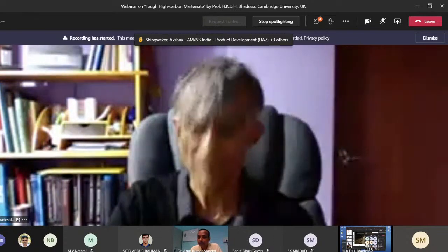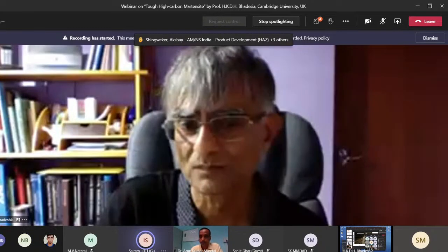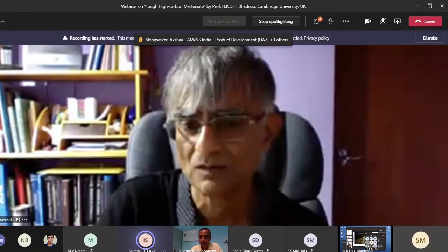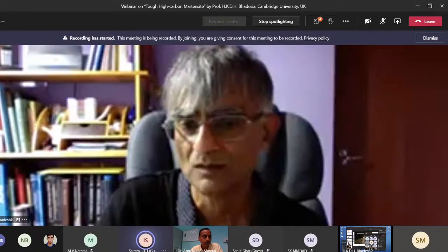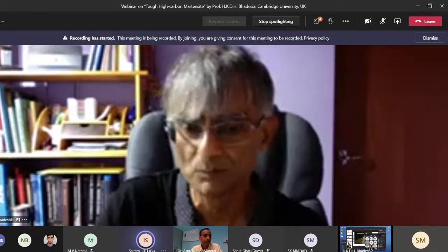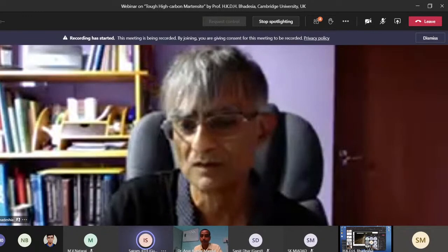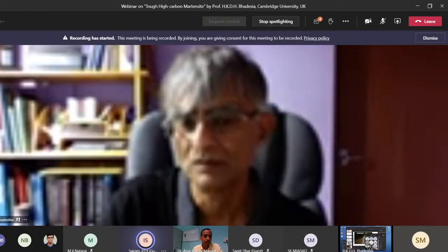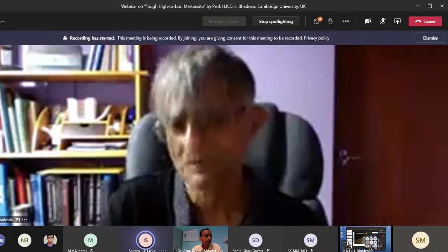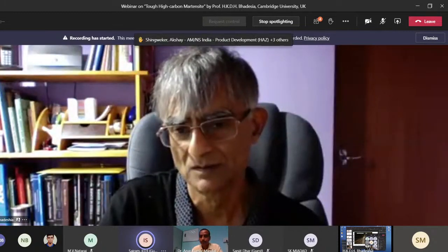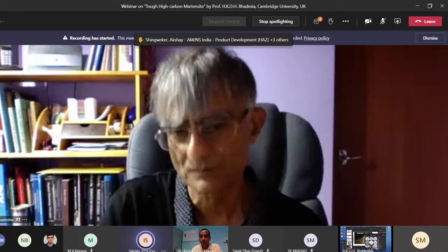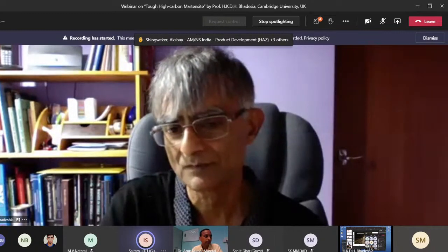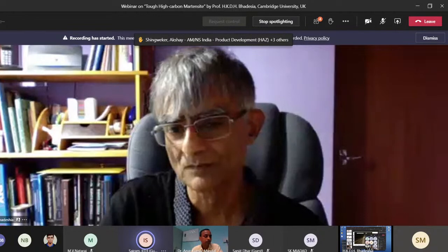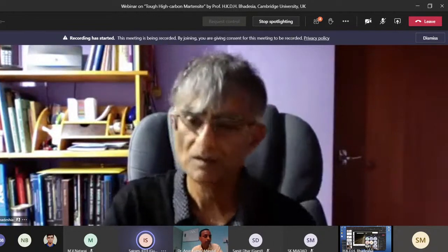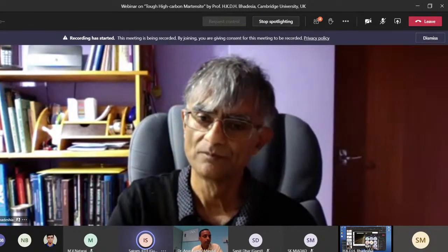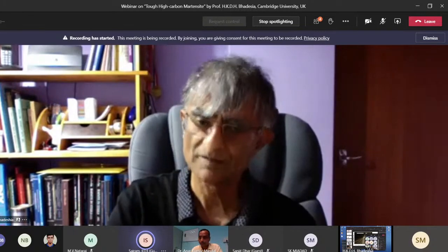Good evening, sir. So my question is, in the present martensitic steel, you have shown that molybdenum addition is mainly for avoiding the impurity embrittlement. Besides that, molybdenum is a good solid solution strengthener and also a BCC stabilizer. And also it is a strong carbide former besides the vanadium and other carbide formers. So by increasing the molybdenum, can we increase the toughness as well as strength of this martensitic steel? Like what is the exact effect of the molybdenum concentration on the martensitic formation?